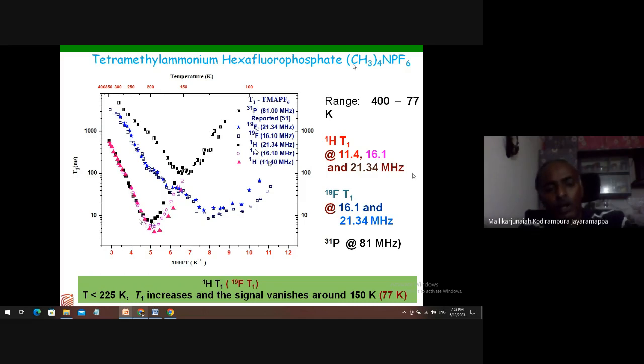From all these things I can estimate the activation energy corresponding to the motion associated with a functional group which has hydrogen. In this case, the functional group is CH3. The activation energy of CH3 motion can be measured from the slope of this curve. In a similar way, at lower temperature, that is for the hydrogen.